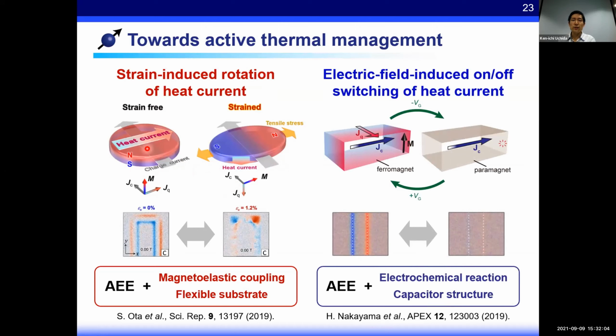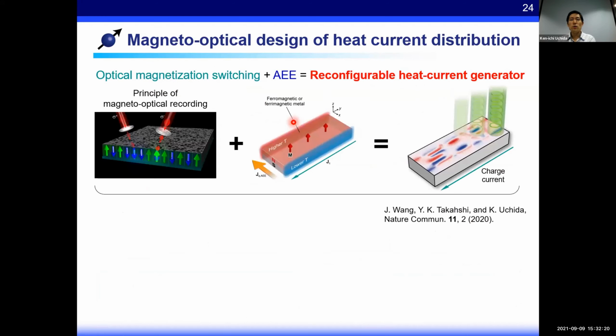We also demonstrated electric-field-induced on-off switching of heat current, which is based on the combination of the anomalous Ettingshausen effect and the electric field effect on magnetism. In addition to these demonstrations, we have also demonstrated a new functionality called magneto-optical design of heat current, which is based on the combination of helicity-dependent all-optical switching of magnetization and the anomalous Ettingshausen effect. By combining these effects, various heating and cooling distributions can be designed by illuminating the magnetic material with circularly polarized light.